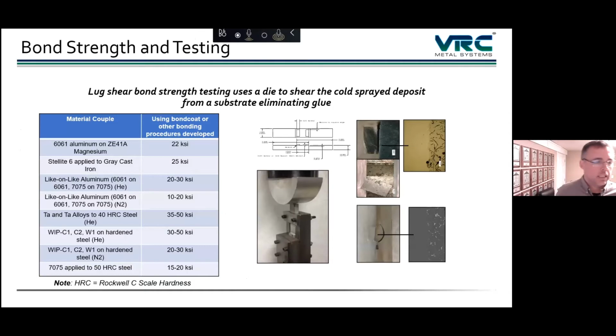So when you do this correctly, you can get numbers like you're seeing here. This is testing that we do. It's a shear type of test where we build up a lug of material on this bar, and then we try to shear those lugs from the surface. And when we do that, we can get numbers that you can see here, like 22 KSI on a magnesium substrate. The yield strength of magnesium is in that 22 KSI range. So the bond strength is actually just about as high as the yield strength of the substrate itself.